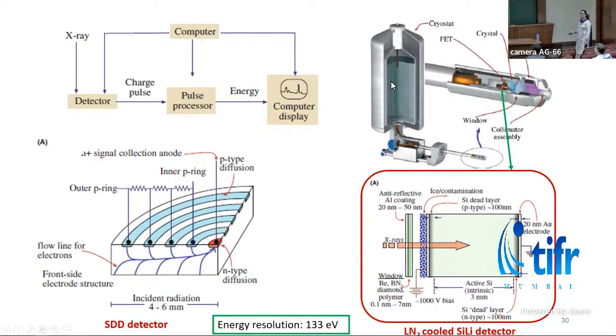But we have these detectors on our Tecnai and Titan TEM. That's why I have included this. These are the new generation detectors, which are SDD, silicon drift detectors. Here on N-type silicon, there are P-type diffusions made in this concentric ring type fashion. This geometry helps to give more throughput. That means more electron hole pairs are created by the number of photons as compared to this detector. This also works at comparatively higher temperature, so it doesn't need liquid nitrogen to be cooled with. And the biasing voltage needed for this detector is 4 times lower than this one. SDD has a resolution of 133 eV.